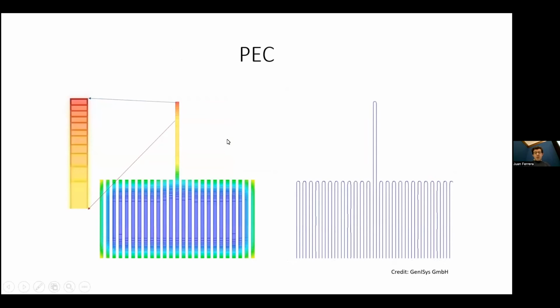So if you put your pattern through the proximity effect correction program, which in our case here at Nano is called Beamer, what the program will do is calculate the error between what you saw in the previous slide and what you want, and it will increase the doses of the pattern such that you get a uniform dose, and your pattern fidelity will be good. So you can see that here in the single line, the doses are increasing.